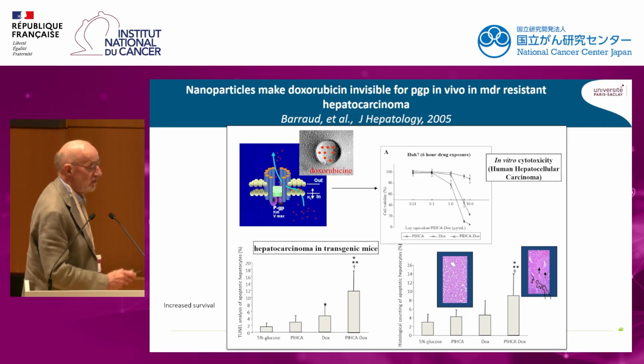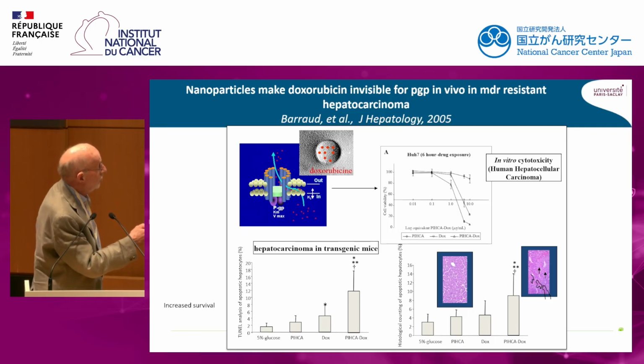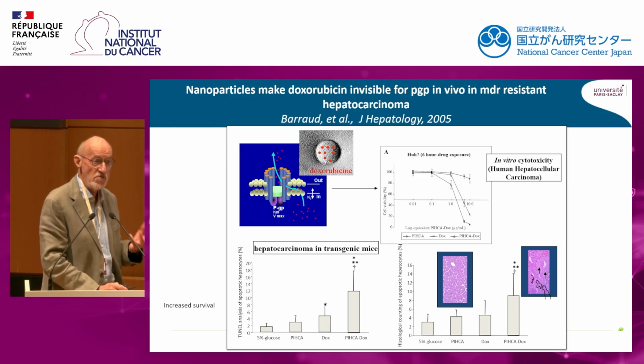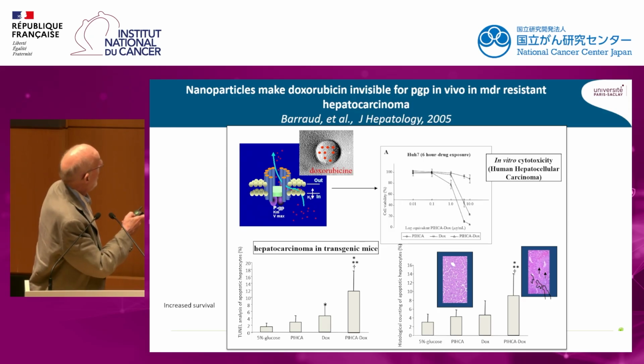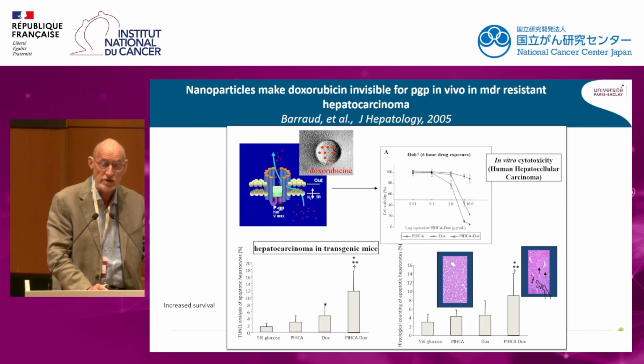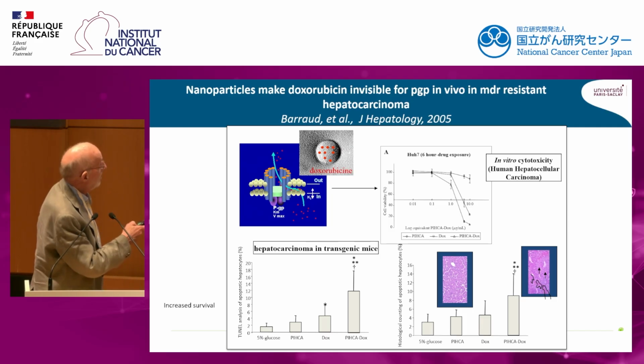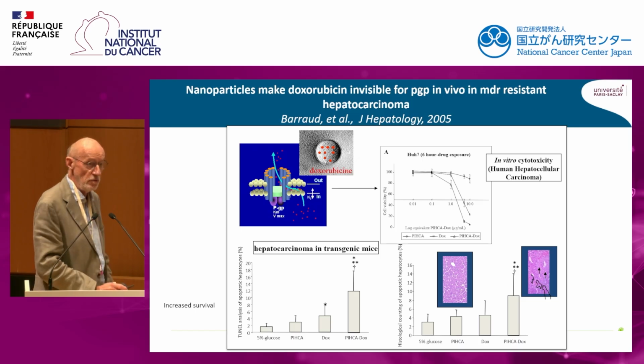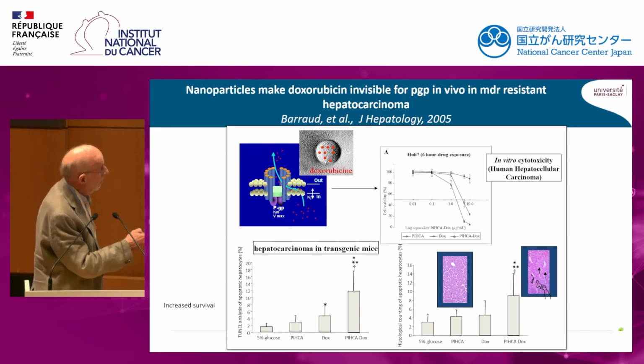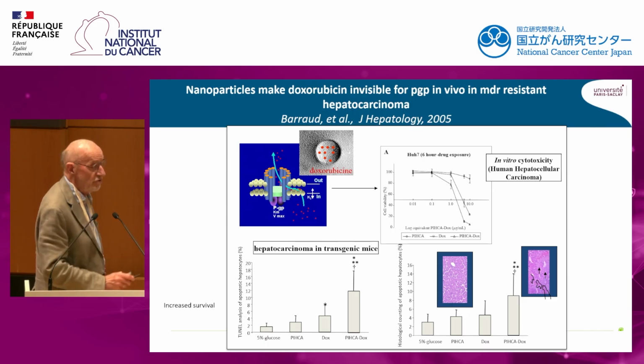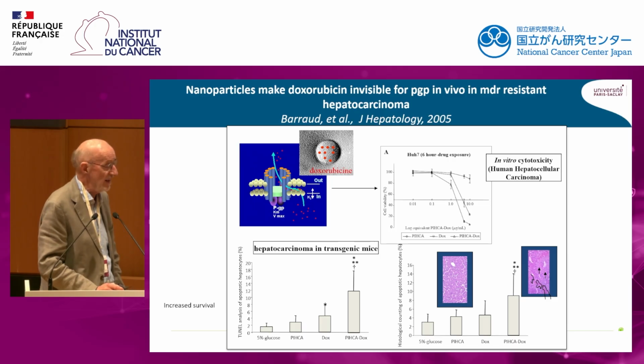And we did here, just to illustrate that, a typical experiment where we took a human hepatocellular carcinoma, and if you are incubating increasing concentration of doxorubicin, you can see that all the cancer cells survive to the chemotherapy. And so the idea we had is to make the doxorubicin invisible for the recognition by the P-glycoprotein by encapsulating the doxorubicin into those nanoparticles. And you can see that it is working quite well, at least in vitro, because after incubation of doxorubicin as nanoparticles, now you are able to restore the sensitivity of those resistant cancer cells.